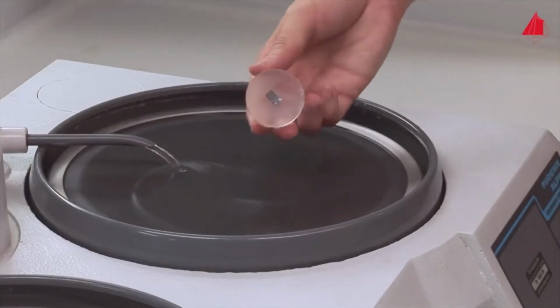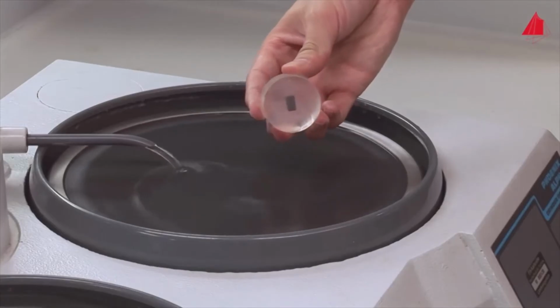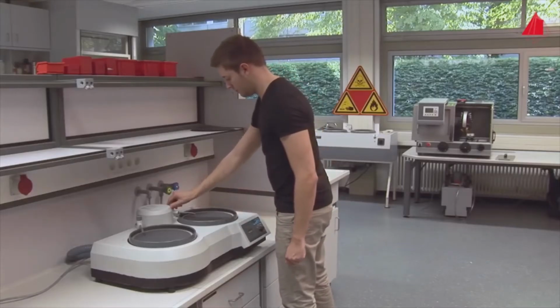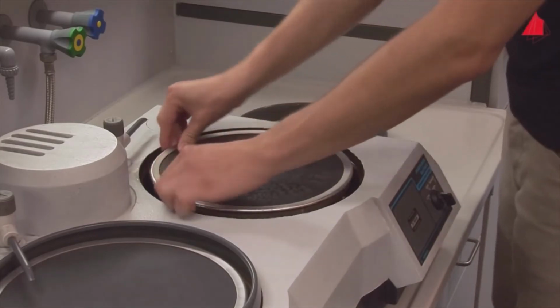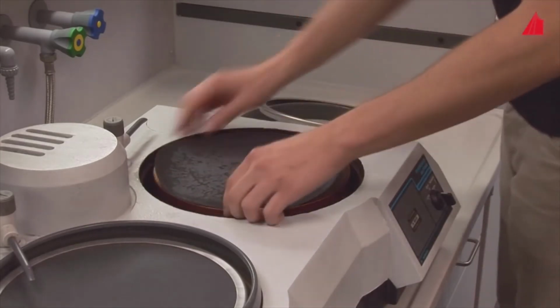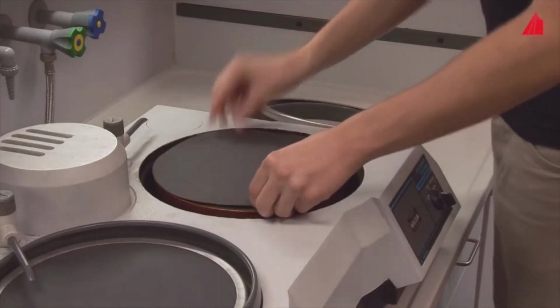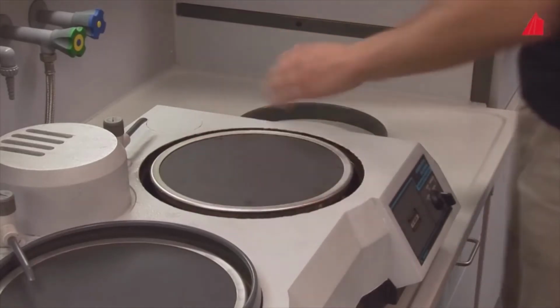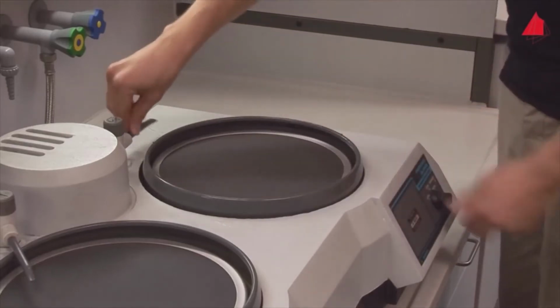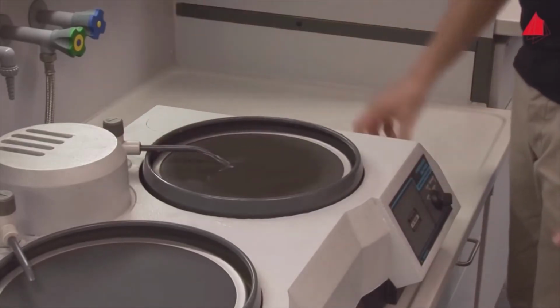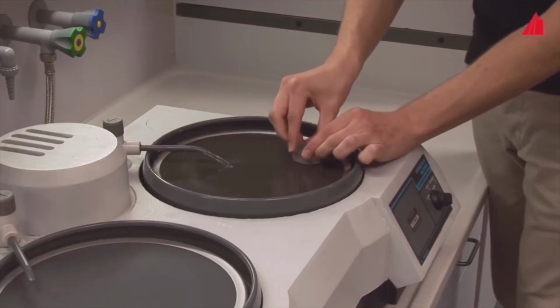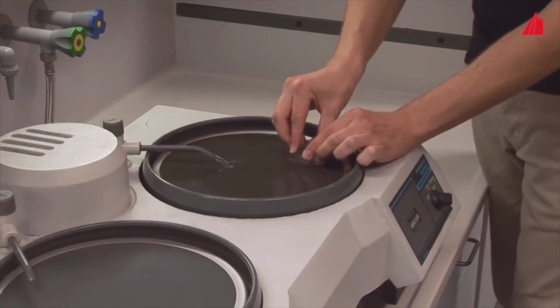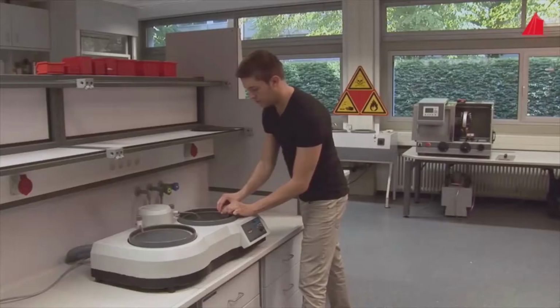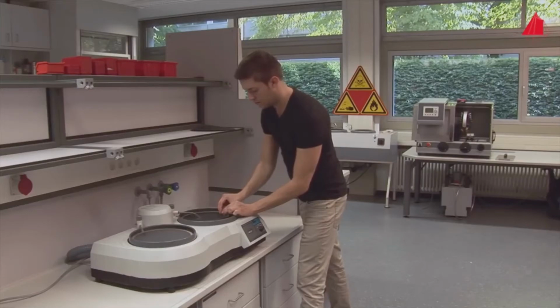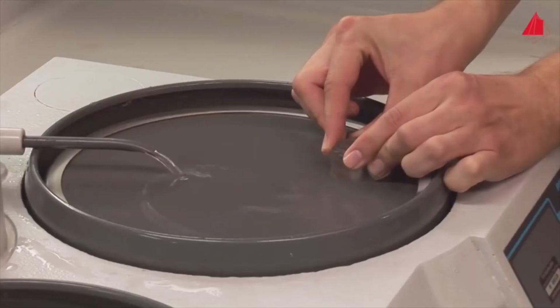Now he has achieved an even, relatively rough surface. The specimen is ready for the next step with finer paper. He inserts a new 320 grit abrasive paper onto the disc. Rotating the specimen by 90 degrees leads to new grinding grooves perpendicular to the old ones. In this way, the material tester can easily check whether the old grinding grooves have been removed completely. It is important to use sufficient water flushing during grinding. This keeps the sample cool and prevents the abrasive paper from being loaded with material particles.